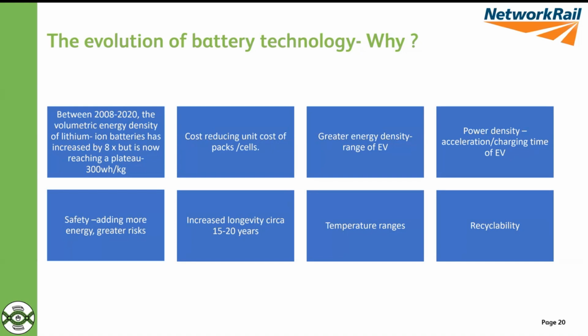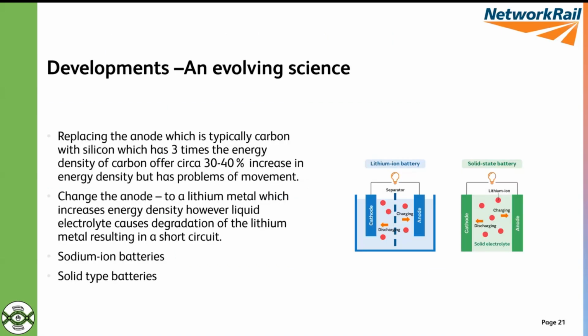If you look at recent developments, they've looked at replacing the anode, which is carbon graphite, with a silicon type arrangement, because that has 3 times the energy density of carbon, and that can increase the battery performance quite significantly. However, there are problems with its expansion and contraction. You have to put it under a lot of compressive stress, which does cause problems. So they've tried to mix some silicon in with other types of products to improve performance. And changing the anode to a lithium metal really does give significant improvement.